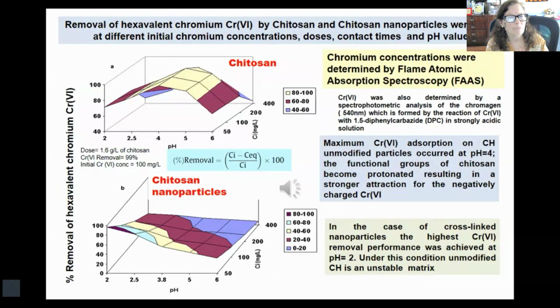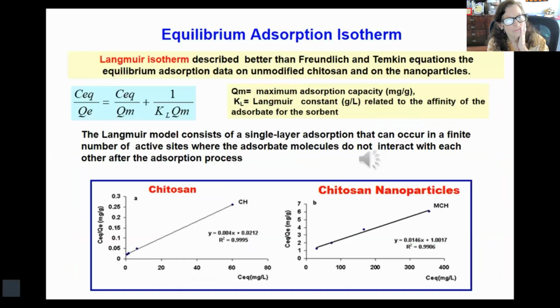Maximum hexavalent chromium adsorption on chitosan unmodified particles occurred at pH of 4. In this case, the functional groups become protonated, resulting in a stronger attraction for the negatively charged hexavalent chromium. In the case of cross-linked nanoparticles, the highest removal performance was achieved at pH of 2. Under this condition, unmodified chitosan is an unstable matrix.